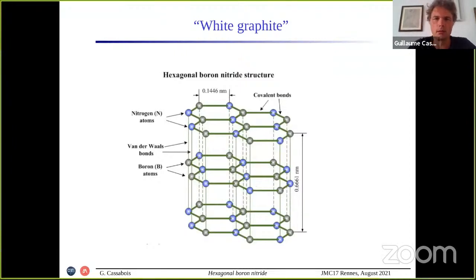It's not completely isostructural to graphite, because in graphite there is a translation from one plane to the other, this familiar AB or Bernal stacking of graphite. In the case of hexagonal boron nitride, the hexagons are perfectly aligned from one layer to the other. So you see, there's nothing really complicated in hexagonal boron nitride. It's only boron and nitrogen, with this very simple crystal structure.